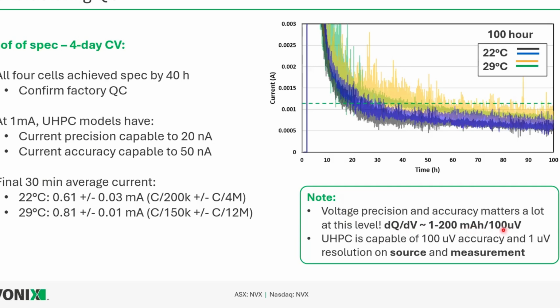If your cell tester is not accurate or precise to much better than 100 microvolts, and you're bit switching or something while trying to hold that cell at 3.6 volts, you'll make massive swings in current or generate lots of noise in your current signal. So this voltage precision and accuracy that's capable with UHPC is actually really important to make this happen. If this test was done on most other cyclers, the noise would be off of this chart.